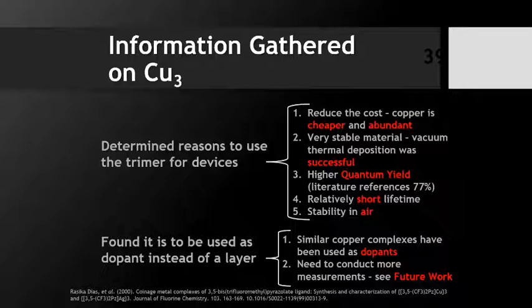We found literature that recommends 77% for this material. It has a relatively short lifetime and is stable in air. It's more stable in air than the materials that we have been working with. Now we found it would be used as a dopant rather than a full layer, which means it would be doped into a host, because similar copper complexes that we found in literature have been used as dopants, and then we need to conduct more measurements of this material.